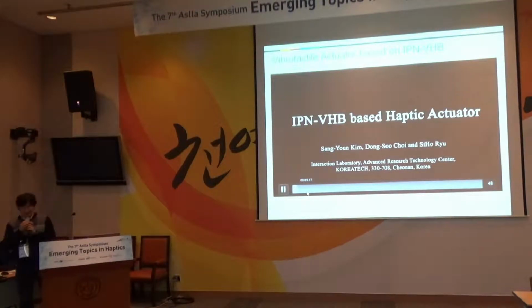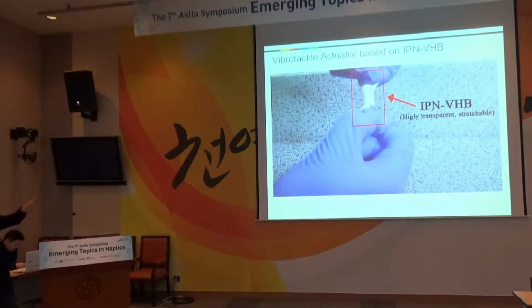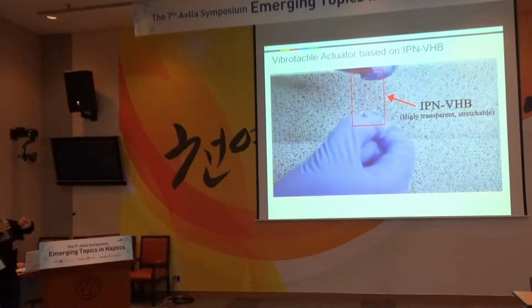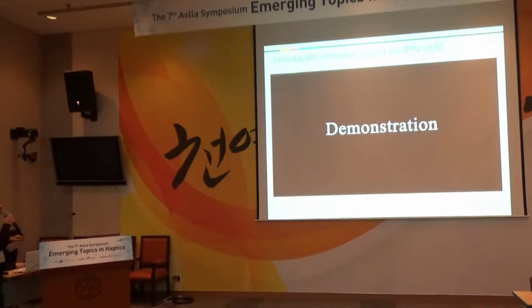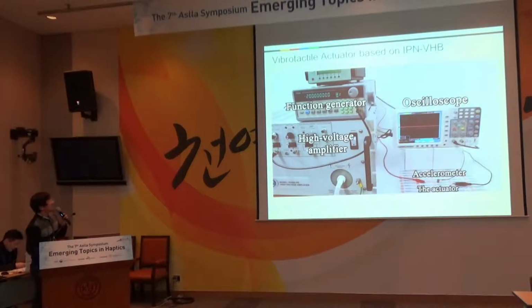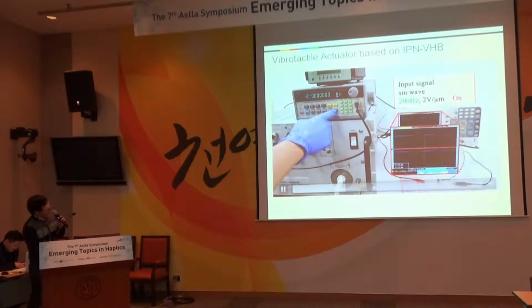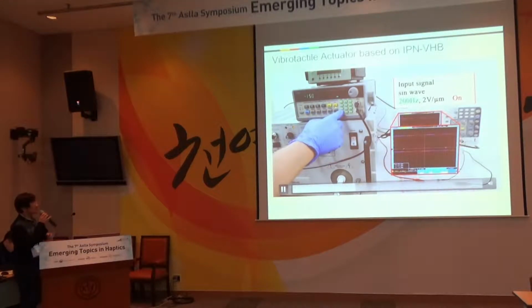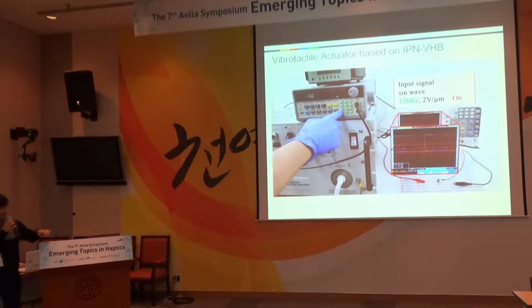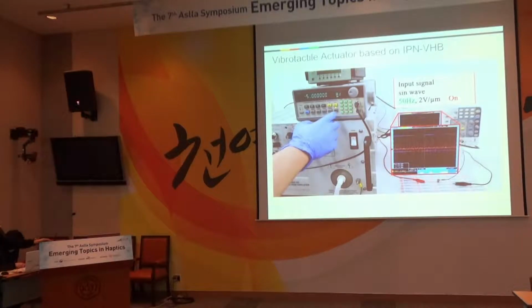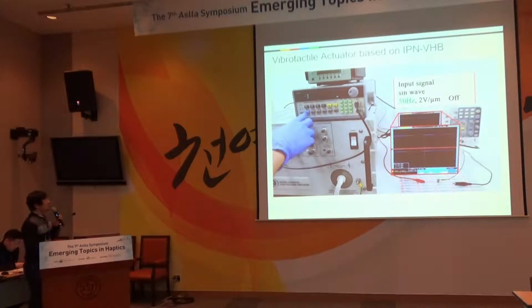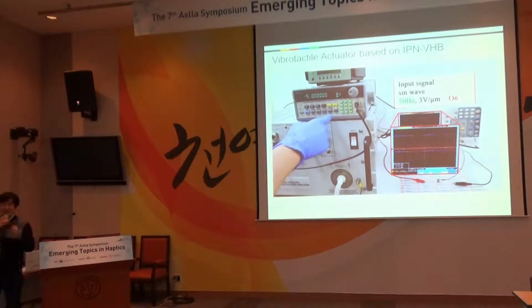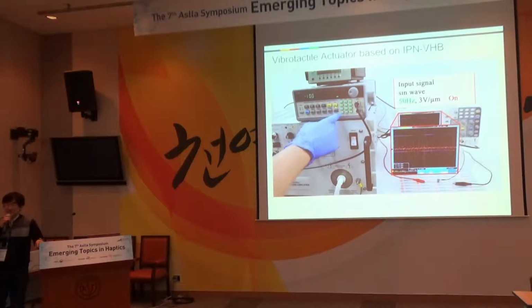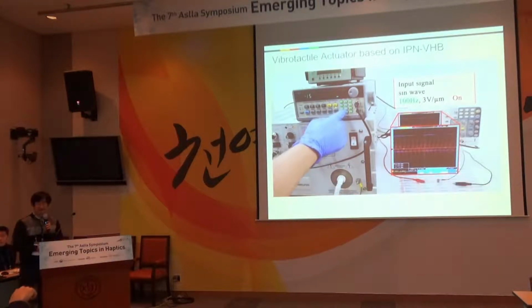And here is an example movie clip of the haptic actuator. You can see it's very transparent and has good stretchability. Then we constructed a special experimental setup and provided voltage with some frequency. As we change the frequency, we can feel this haptic sensation, and as we increase the voltage, the magnitude of vibration increases. The resonance frequency is about 200 hertz maybe. Did you measure it with LDV? Yeah.